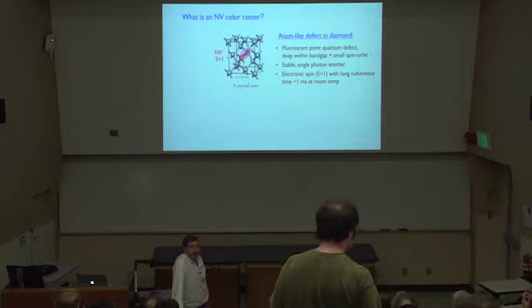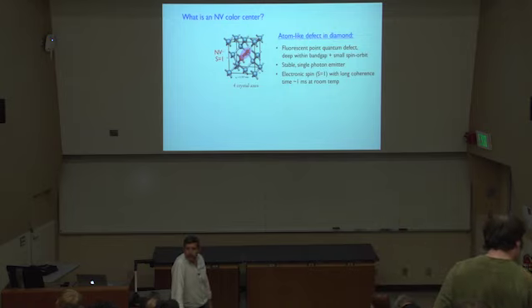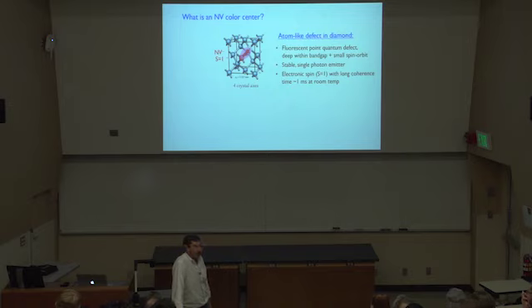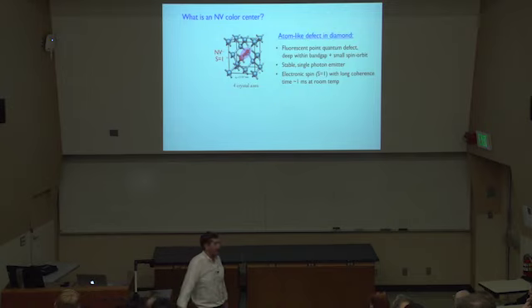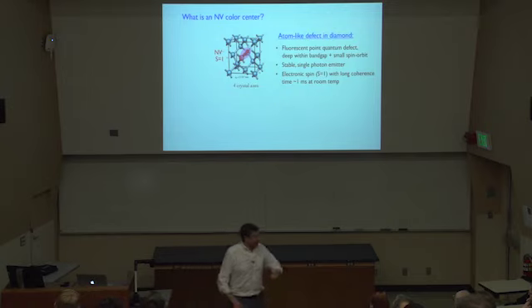That means the NV picks up an extra electron, and that's the energetically favorable state. By the way, also the vacancy being next to the nitrogen is energetically favorable. When you fabricate the NVs inside the diamond, either in the chemical vapor deposition process grown in while you're making the diamond in a laboratory, or by implanting nitrogen ions afterwards, you then anneal the diamond to mobilize vacancies. They move around inside the lattice, tend to find the nitrogens and form NVs, and that's energetically favorable, the process to do that.